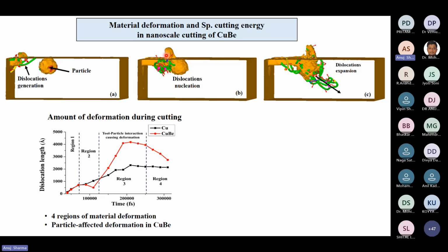But after the tool faces this hard particle, it starts pushing the hard particle. So this hard particle itself forces the copper material ahead of it. A lot of dislocations are generated because of the force that is coming from the hard particle, which is in turn coming from the cutting tool. So a lot of subsurface damage was occurring due to this hard particle.